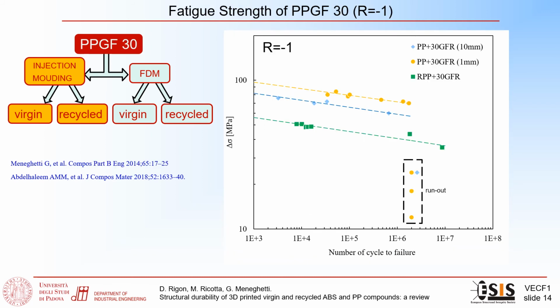Finally, we have the fatigue test results related to PPGF 30. Two different fiber lengths were considered in the virgin injection molded PPGF, and the relevant results are the blue and the yellow ones. The recycled PPGF 30 is reported with the green square marker. As you can see, the recycled PPGF has approximately 30% lower fatigue strength with respect to the virgin material.